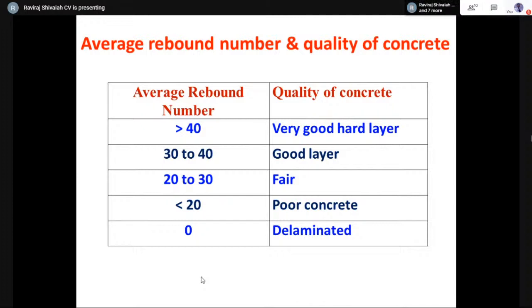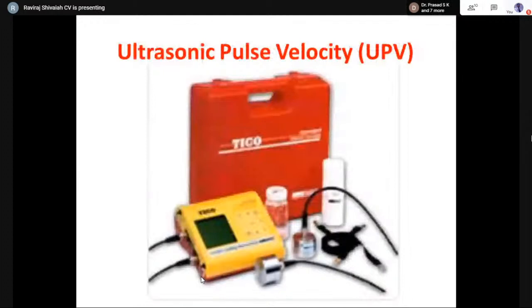So we would always try to work with numbers rather than directly trying to link that with compressive strength, especially with rebound numbers. So if you have values of 30 to 40, we have to be happy, and then we have to take some other tests to justify that the quality of the concrete is consistent and good in other tests also.